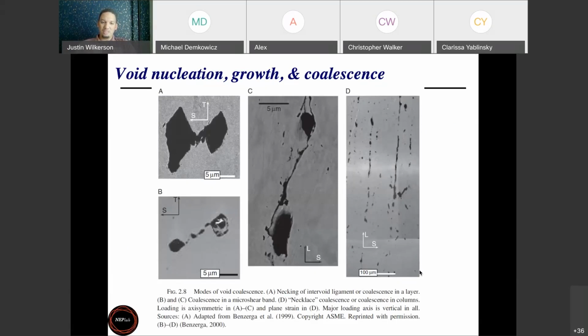One good thing that makes life a little bit easier is that coalescence is probably the one thing that's way more complicated to model under quasi-static loading conditions than under dynamic spall type loading conditions. So we tend to see, for the most part, voids staying fairly spherical at very high rates, and they just grow until they touch each other. So coalescence modeling doesn't seem to be as big a deal at very high rates as it is at low rates.